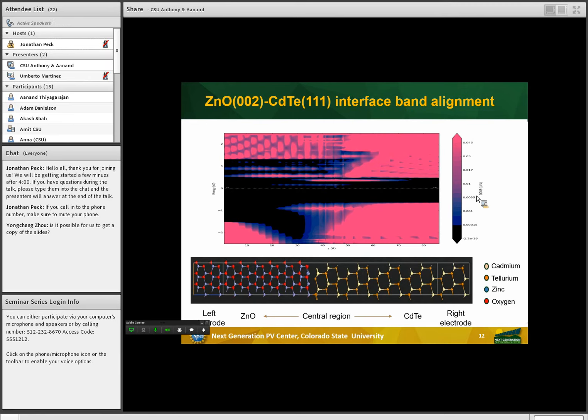This is also a two-probe model using DFT with non-equilibrium Green's function. On the left, we have the left electrode, we have zinc oxide, and on the right, we have cadmium telluride, and the central region basically is where the interface is. Since it was hard to find a suitable interface potential between these materials, they were relaxed using theory.